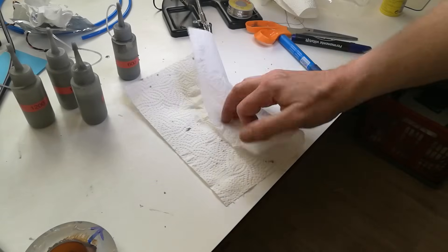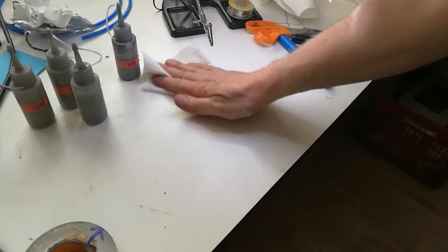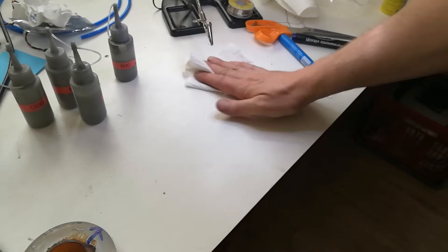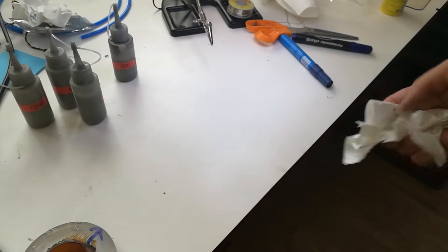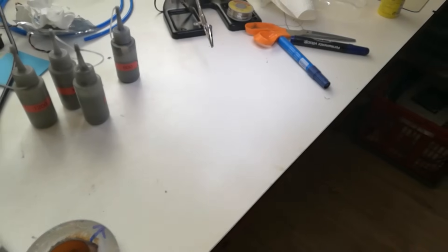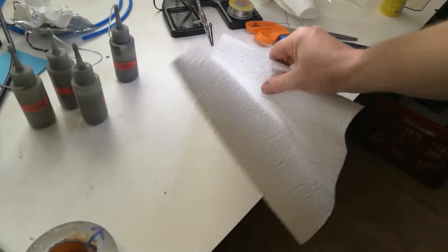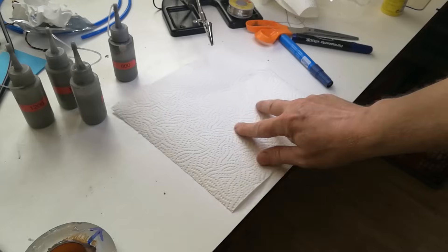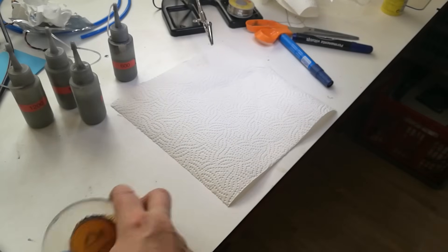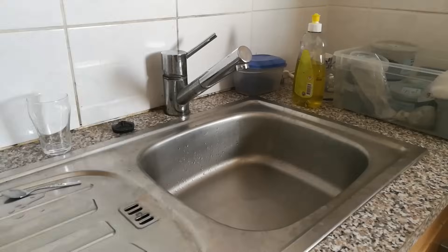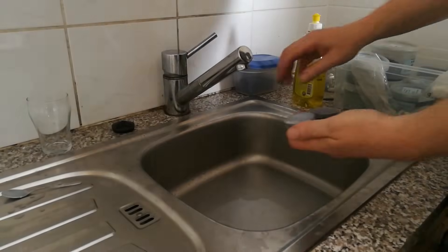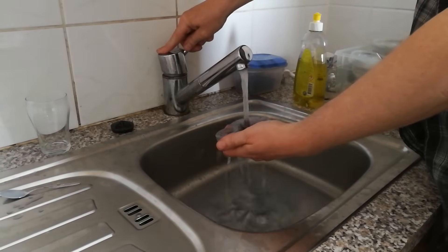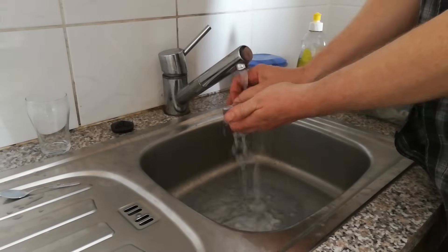Between working with different grains, the surfaces and the working space should be carefully cleaned in order to avoid contamination with larger grains later in the process. A larger grain can cause a nasty scratch, which can cause a lot of time to remove again. For this reason I never wear shirts with long sleeves when I grind, since these are notorious for collecting particles and releasing them somewhere later in the process when you are fine grinding.